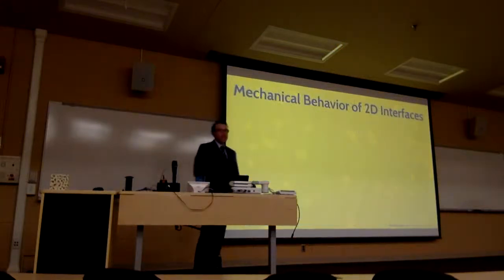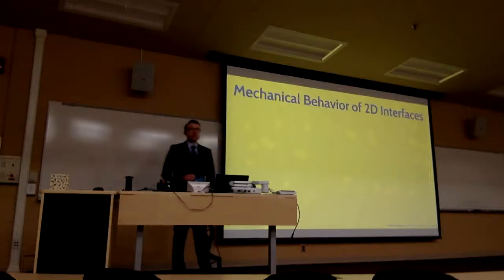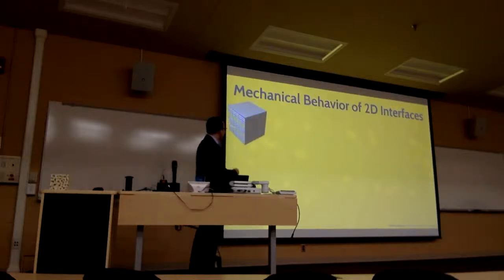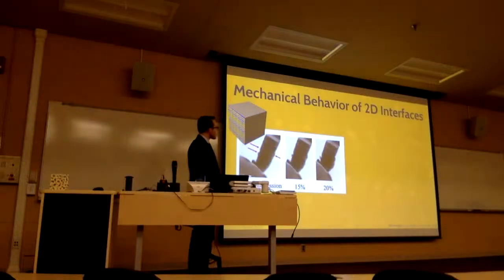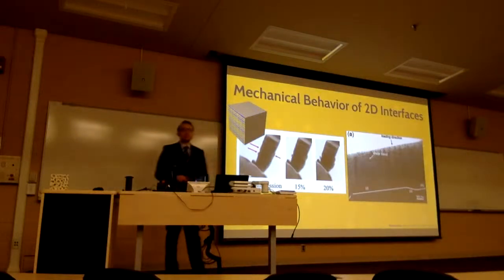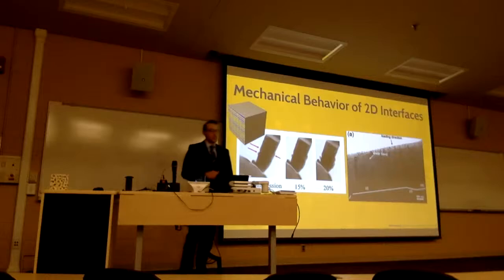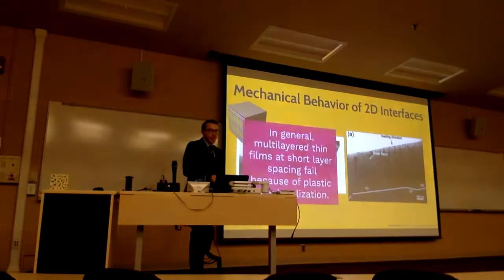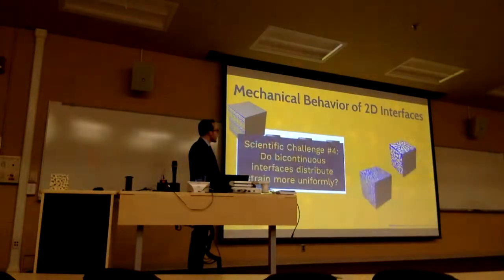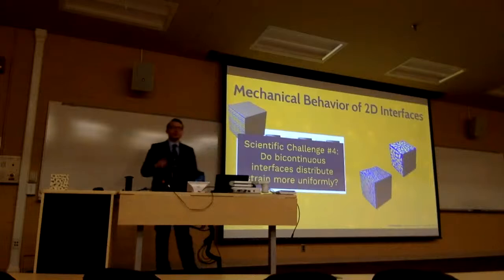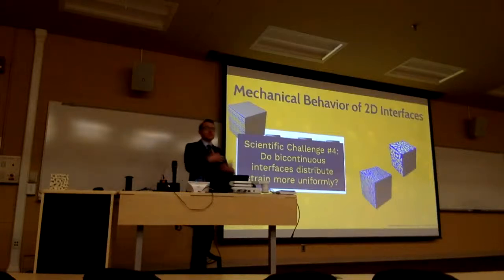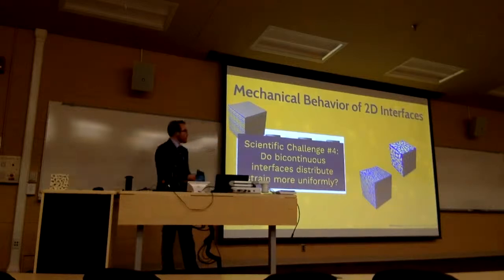So we know how 2D materials, or materials with 2D interfaces, behave, like the one I imaged here. Under compression, they behave like a brittle material. All the plastic flow in the material localizes into a single shear band, and the material fails very suddenly, because of flow localization. The scientific challenge here is: do bicontinuous interfaces, when we extend those interfaces in 3 dimensions, distribute strain much more uniformly? We have these types of morphologies that we can play with.